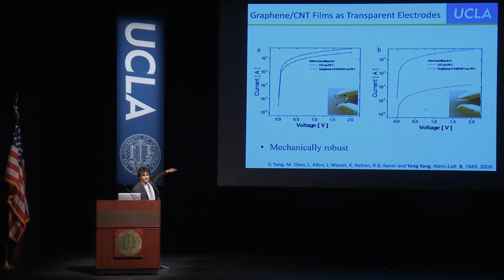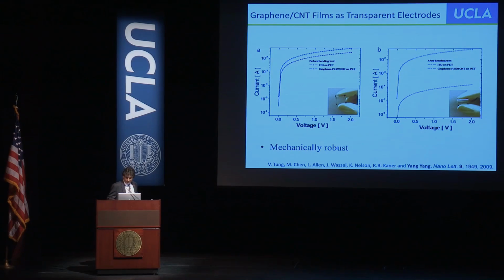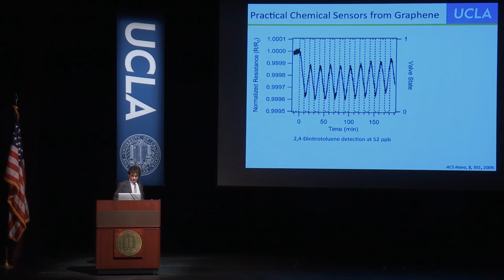Well, the indium tin oxide is a nice crystalline inorganic solid, and you bend it 10 times, the conductivity drops by a factor of 1,000. When you bend our carbon nanotubes and our graphene, nothing happens. And so you can actually make flexible electronics out of this. And many companies are now looking at thin sheets of carbon for electronics. And you'll start seeing flexible cell phones, other flexible electronic devices.